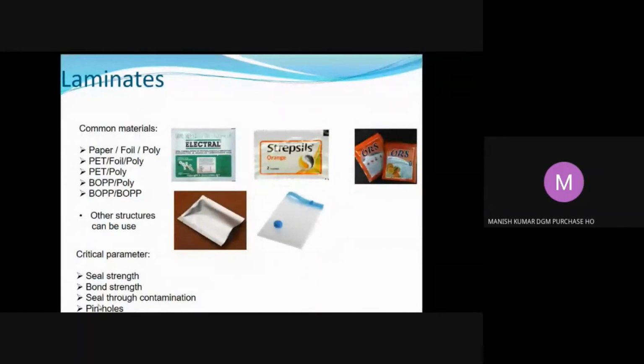Another important thing is pinholes. All laminates should be pinhole free. Pinholes basically come in aluminum foil structures, so you have to check the pouches and store them properly. If it is coming in roll form, you should handle it properly so that it is pinhole free. There should not be creasing in the pouches. Otherwise, it will create pinholes and your product will fail.